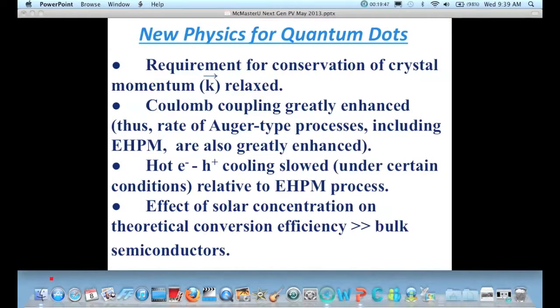But in a quantum dot solar cell, you have the same voltage. It's changed because the quantization increases the band gap, so you can control the band gap of the same material by just controlling its size and thus its voltage. But you get this increase in current. And then finally, there's a very interesting effect when you use solar concentration with carrier multiplication. You get a huge increase in efficiency, which approaches about 80% when you're up around 500 suns or 1,000 suns.